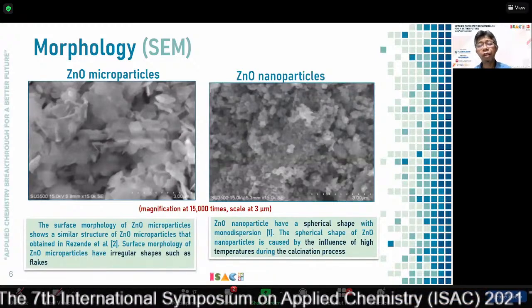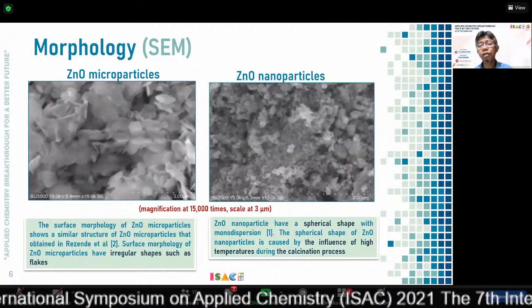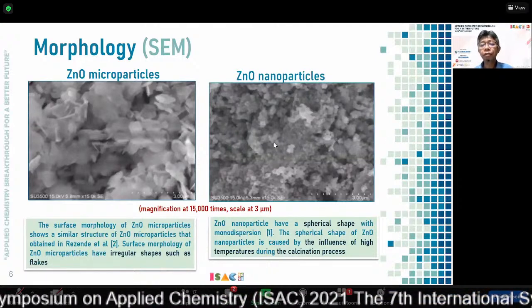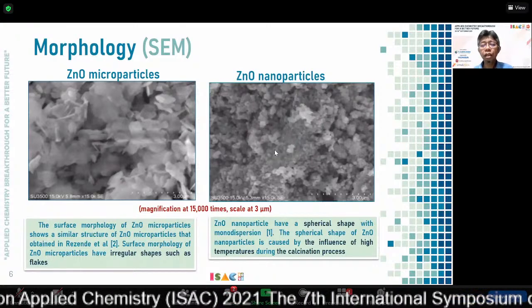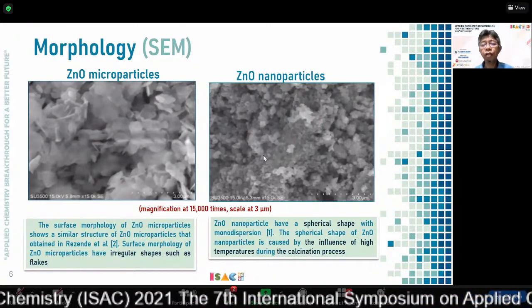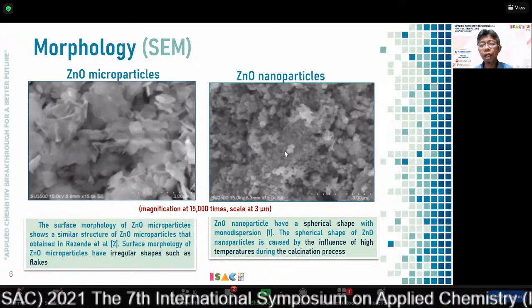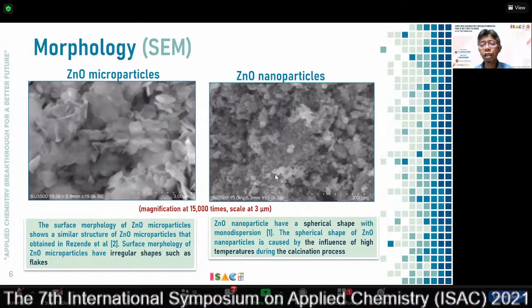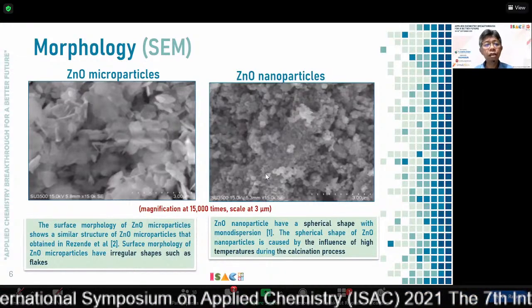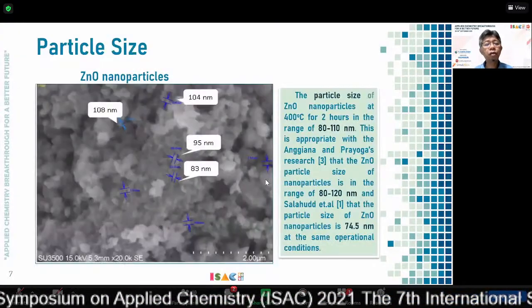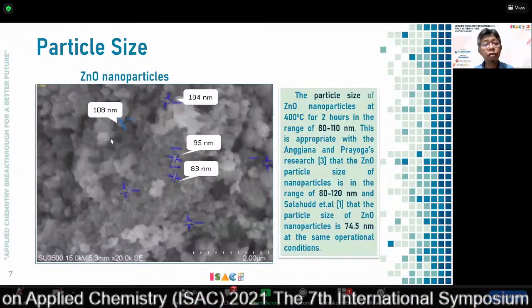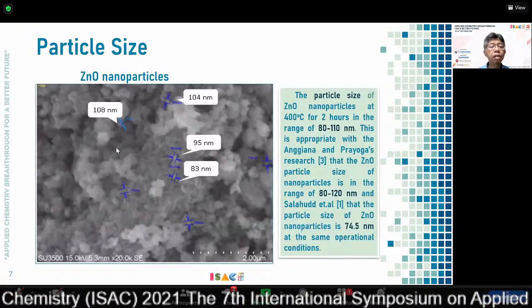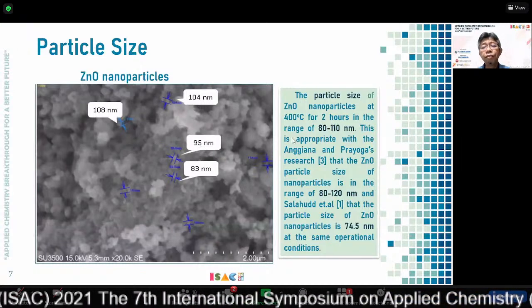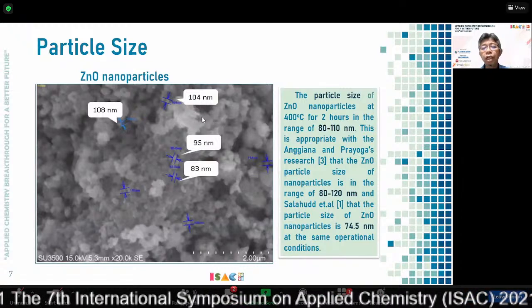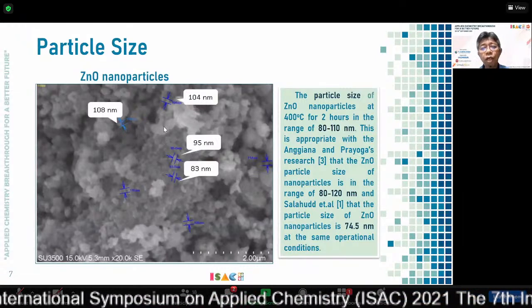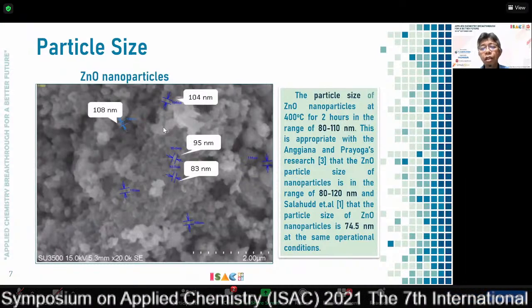On the other hand, the zinc oxide nanoparticles show a spherical shape, and this is due to the influence of the capping agent as well as the calcination step. The particle size, especially for the zinc oxide nanoparticles, we tried to observe by using software, and it was obtained in the range of 80 up to 110 nanometers.